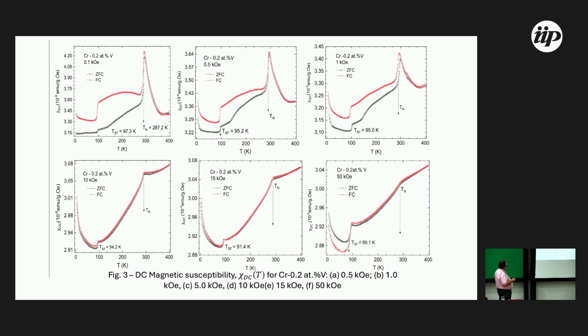This is 0.2, the same behavior. Compare this jump with this jump. And when cooling down the sample with applied magnetic field, there is no reversible behavior. Decreasing to this point, where the magnetic moment starts and this behavior appears. This behavior, remember, is from the ferromagnetic interaction.